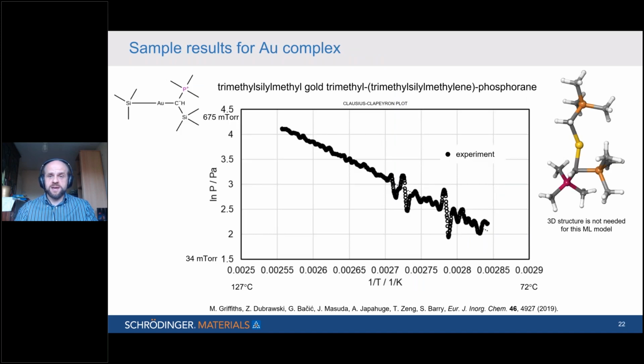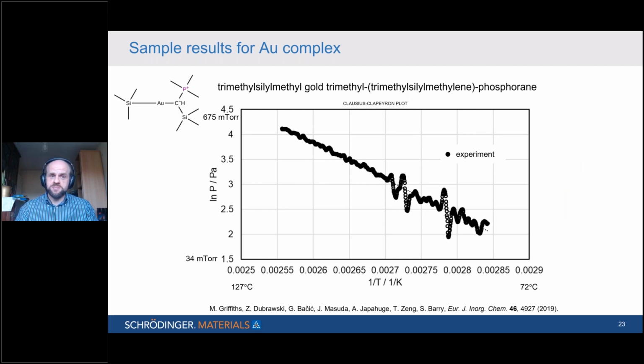Here's one specific example from that gold set. It's a complex, trimethylsilyl gold with a trimethylsilylmethylene phosphorane. And this comes from the group of Sean Barry at Carleton University. And these experimental data are Clausius-Clapeyron plots, so the log of the pressure against 1 over temperature, derived from thermogravimetric experiments. And I've shown the 3D structure just to give you an idea of what the structure is, but in fact, you don't need it for this model. You just need the 2D sketch, as I said before.